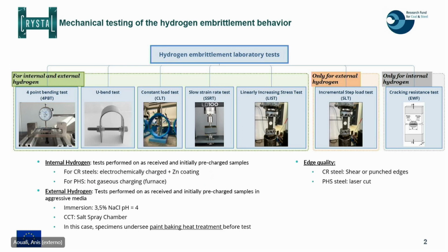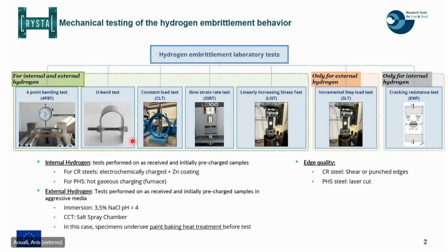The first two tests have bending solicitation, the famous or well-known 4-point bending test. I will go in detail for this test later. The U-bend test, which is used to simulate the forming process. And as you can see here, we simulate the bend, and then we use the screw in order to keep the sample under deformation. The other test is the constant load test, and the principle of this test is to impose a constant displacement using this kind of device, which is called the proof ring device, and which acts as a spring and maintains the sample under constant displacement.